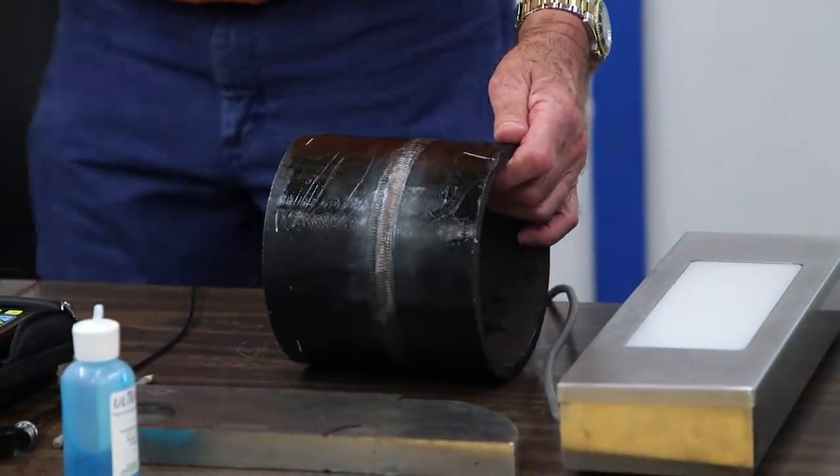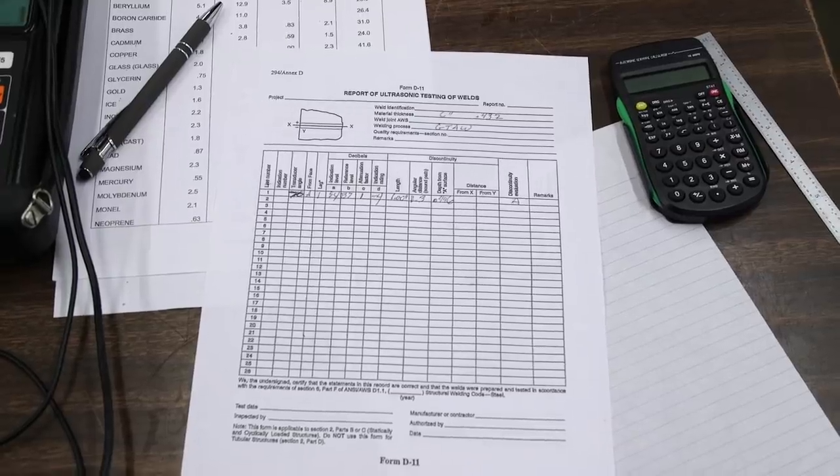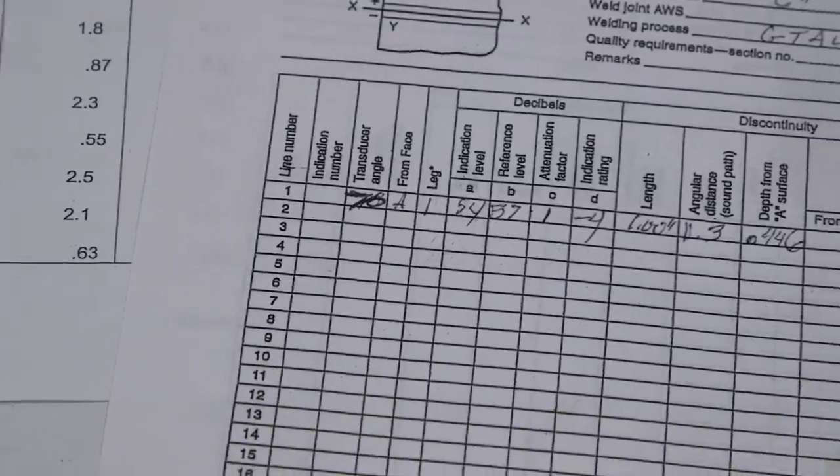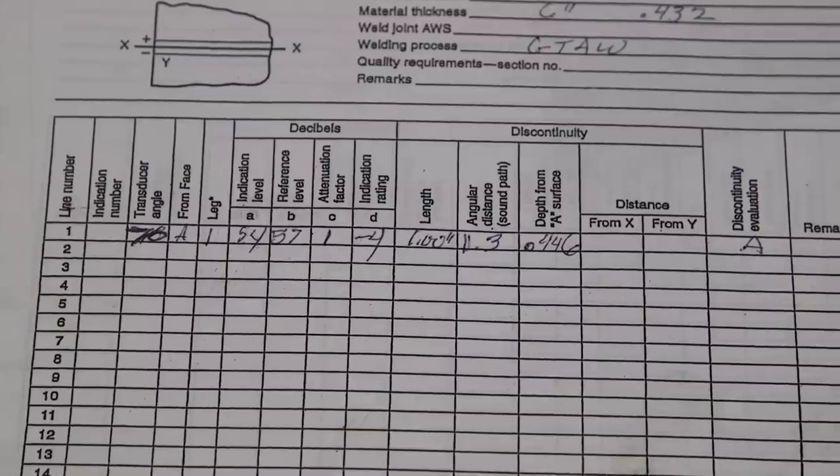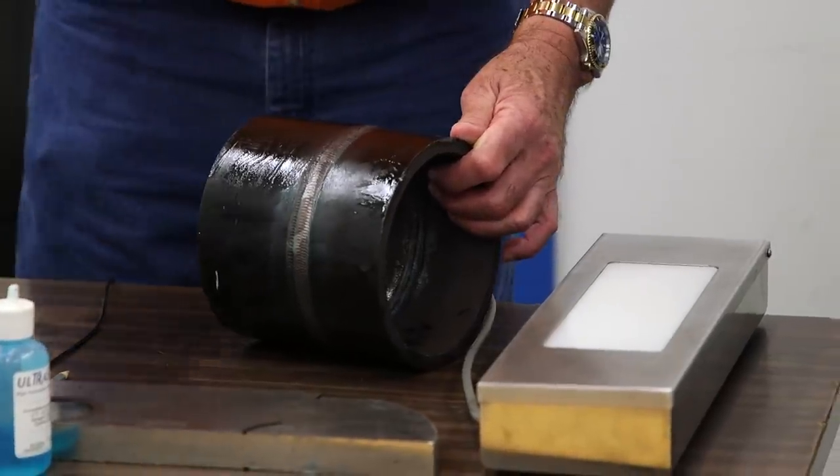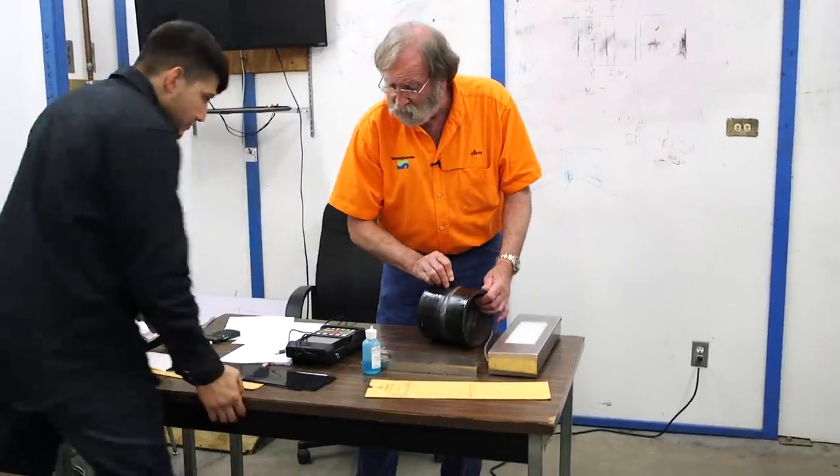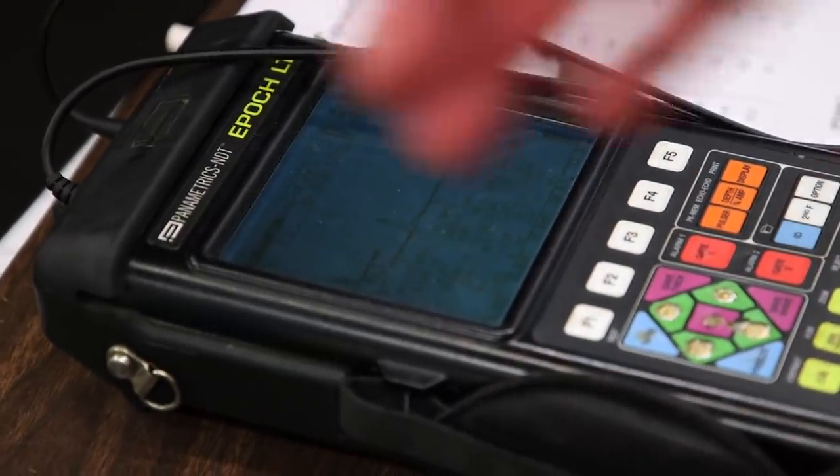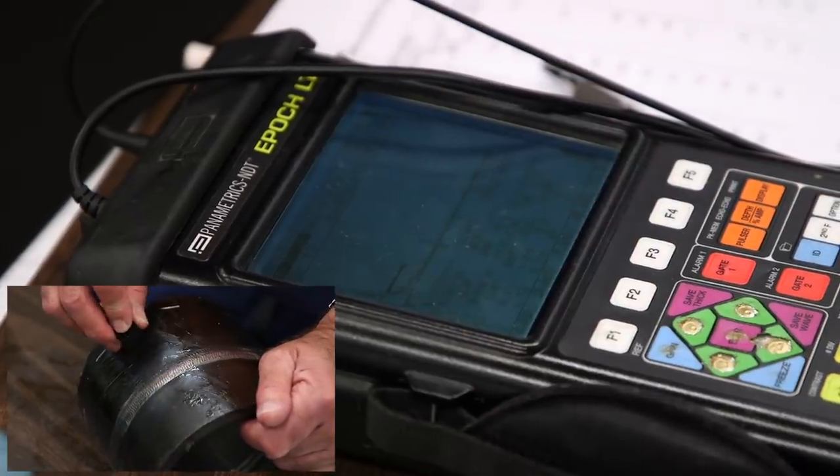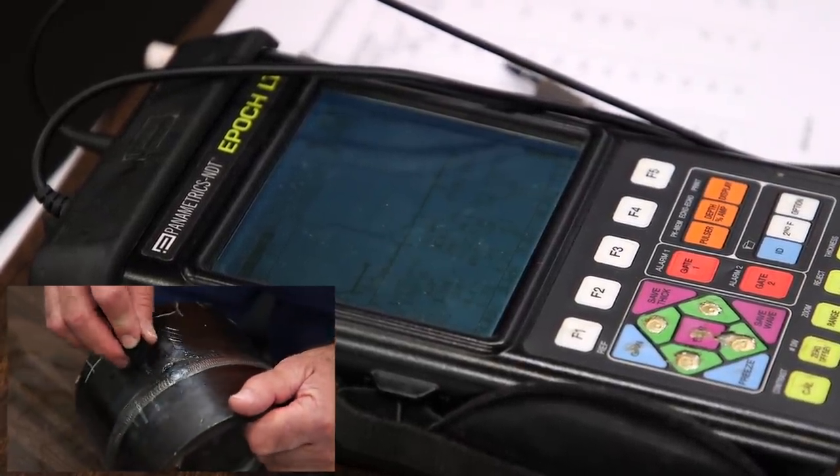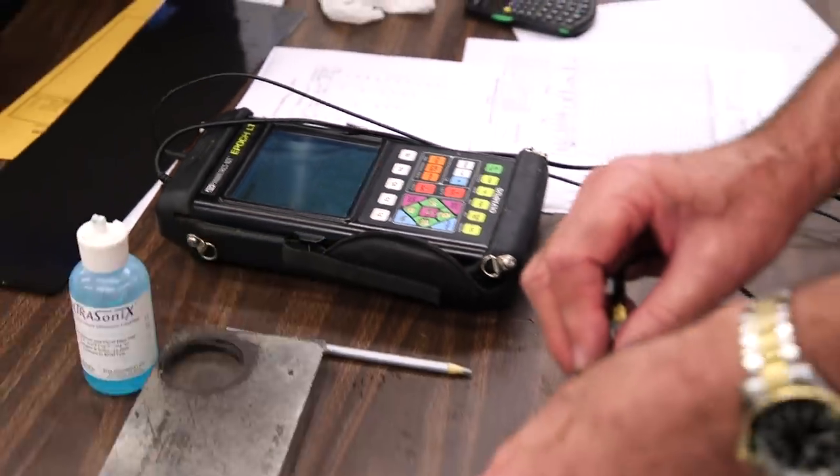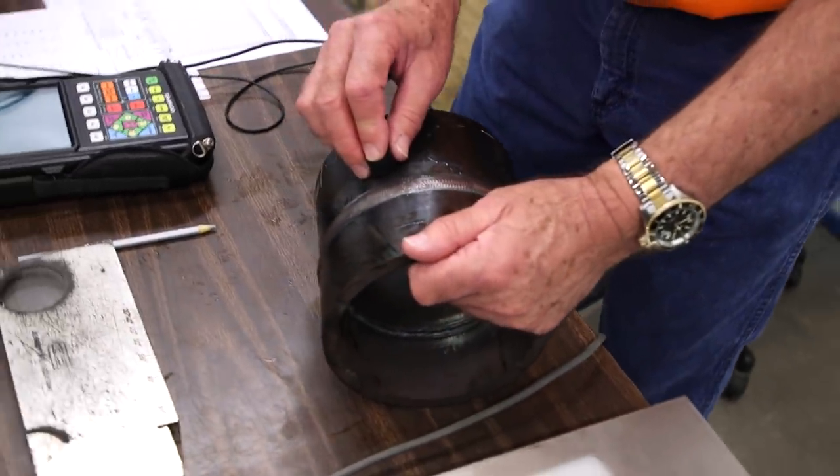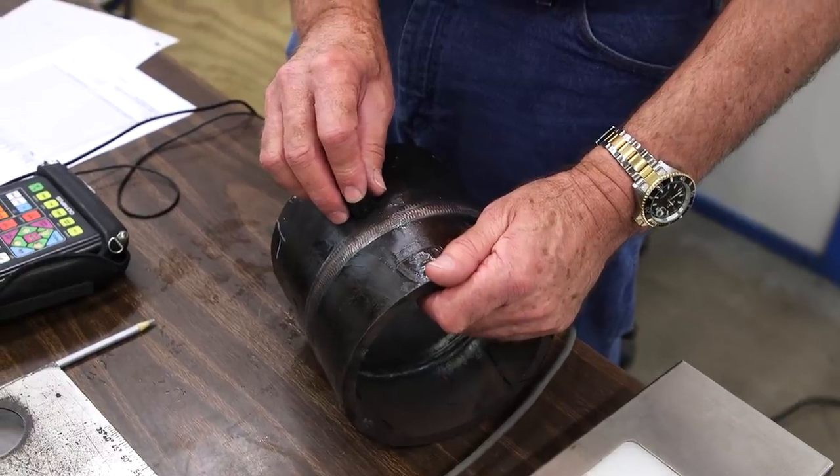This is a AWS calculation sheet that I've put together when I started to do this. It tells me we're gonna be using a 70-degree transducer, and let's just see what the heck we see when we start out. We'll work our way all the way around this. So if you want to take a look at the screen here, we won't see a heck of a lot coming up here. Now, you see that little guy coming up at four inches? That's this side right here. It's about four inches from about here to here. So that's where we know what we're looking at. So we got this back side. In the middle here, I don't see much going on. That's just gonna be an echo. That doesn't mean much anything there.